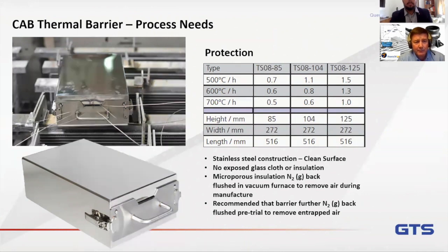You'll notice at the front of the barrier there's like a drawer which you pull out. Now in that drawer, the microporous insulation and the glass cloth is completely encased in a metal structure. So the direct contact with that and potential contamination from hydrofluoric acid is eliminated completely. So it removes the risk of deterioration of the thermal barrier.